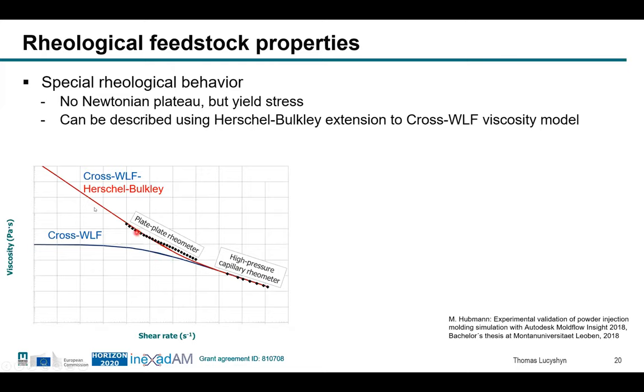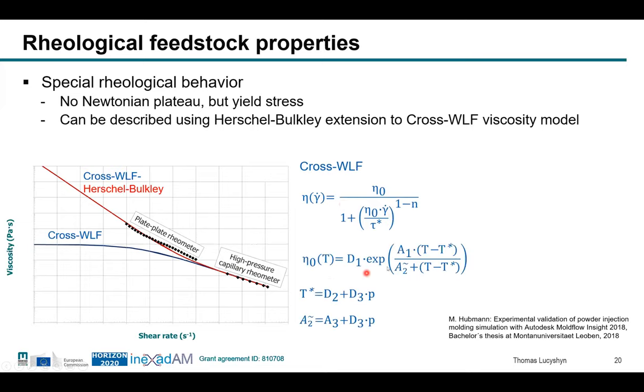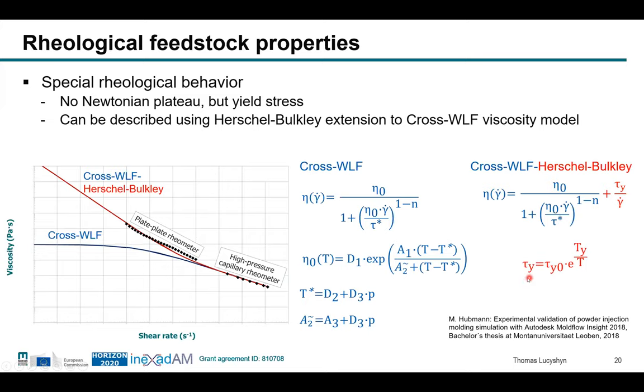And this increase of the viscosity can be described with this Herschel-Bulkley extension. So you take your Cross-WLF equation, I don't have to discuss it: viscosity as a function of the shear rate, and again the viscosity as a function of temperature and pressure. And then you extend this equation by an additional term, which consists of this yield stress term divided by the shear rate. And the yield stress itself can also be described as a function of temperature. So using this equation, you can describe this behavior in a sufficient way. And this behavior had to be implemented in Moldflow as a user subroutine.